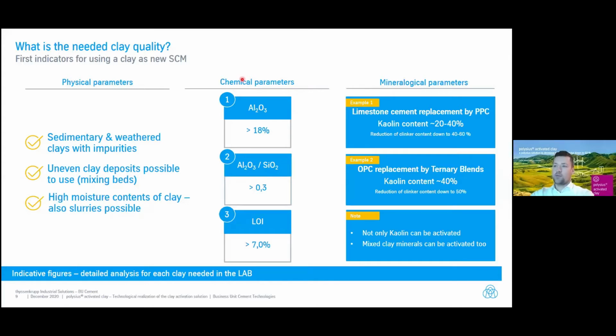If we now come to the chemical parameters, then there is a certain demand on alumina oxide within the clay. There is a certain ratio which is needed between alumina as well as silicon, and the LOI should be above 7%. So this is just a very, very rough estimation. So if you just have the chemical data available of your quarry, for example, then you can check these figures.